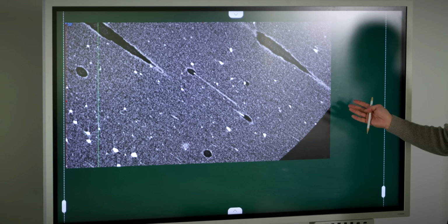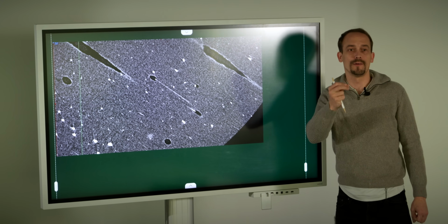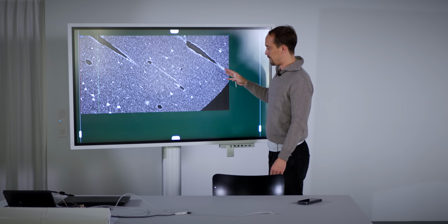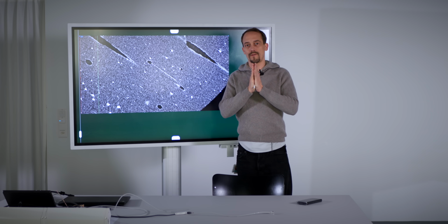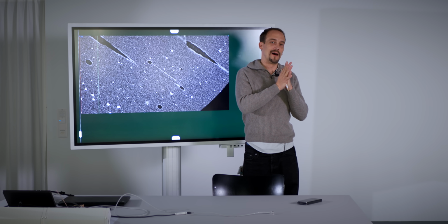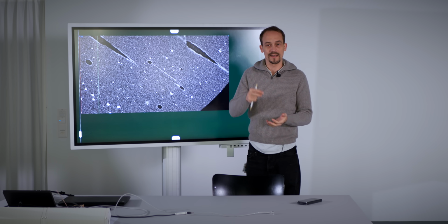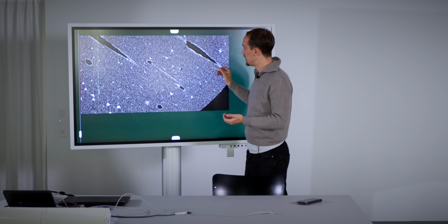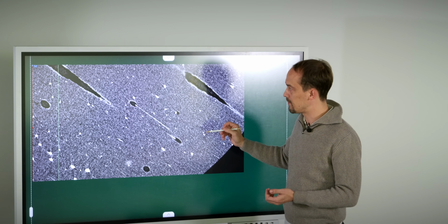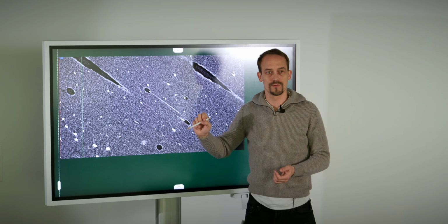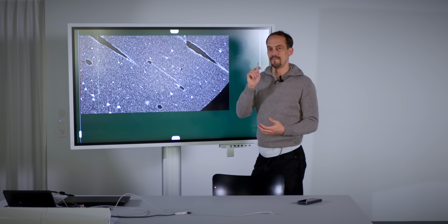So this now is a close-up of the carbon fibers inside of the material. First of all, one thing we can already confirm, what we already saw in our microscopy images: the carbon fiber actually stays within the extrusion. You don't have carbon fibers on the sides of your extrusion. I found something else very interesting.